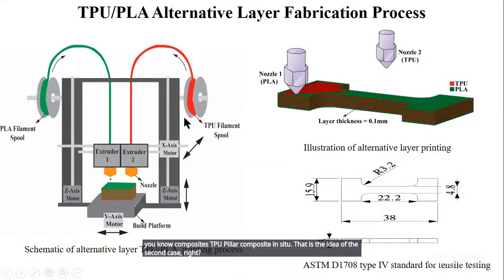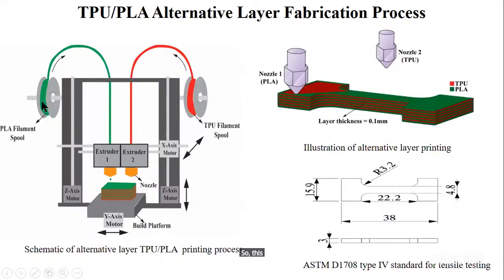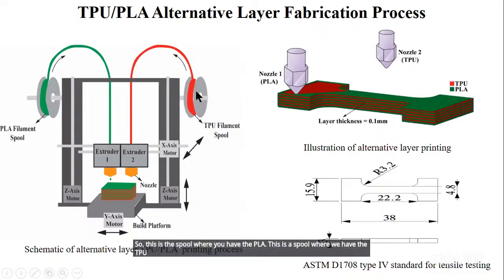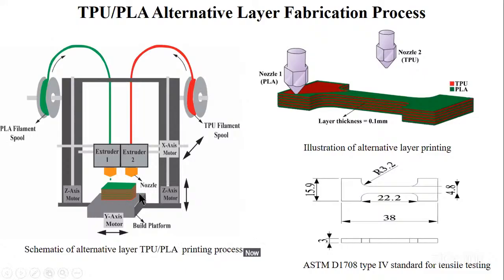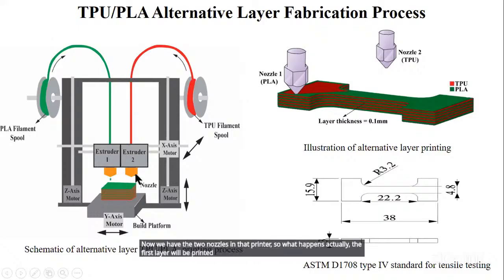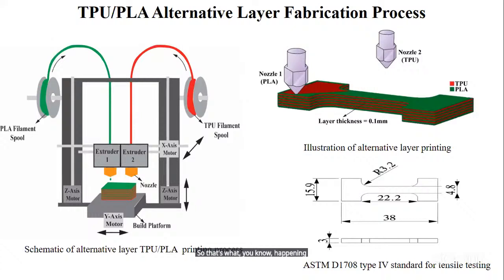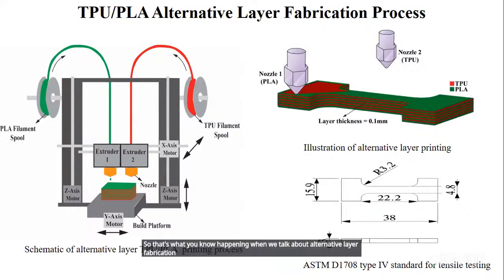You can see clearly this schematic explains the alternative layer fabrication of TPU PLA composites. This is the spool where we have the PLA, and this is the spool where we have the TPU, which is red in color. We have two nozzles in that printer. The first layer will be printed by the PLA, and the second layer will be printed by the second extruder with the TPU. That's what happens in alternative layer fabrication for making the TPU PLA composite material.